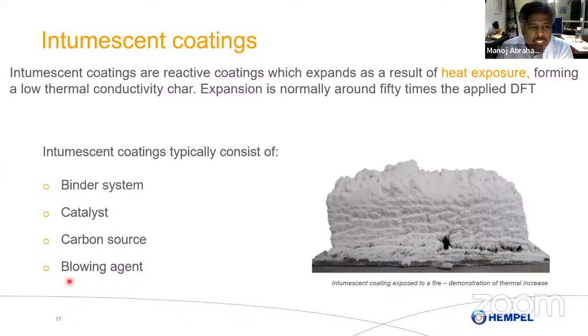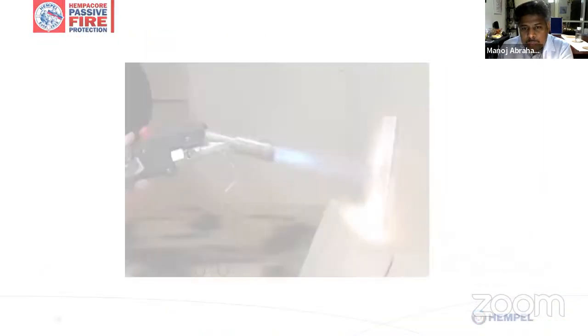So slowly carbon starts coming out because of this catalyst acid reaction. And this blowing agent, like melamine, starts to give out small bubbles of inert gas like nitrogen, and this bubble along with the carbon material slowly moves up. It pushes up and forms an insulating foam. So the heat coming in from the outside will not go in directly, and it will not go quickly, it will slow down. So this is an insulating foam that has formed. And this foam will ensure that the steel does not reach the critical temperature. So this is primarily what we are doing here.